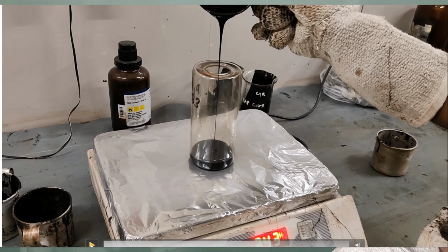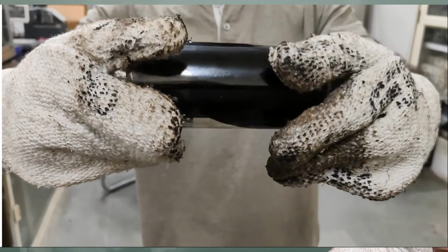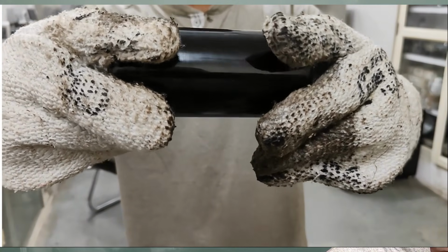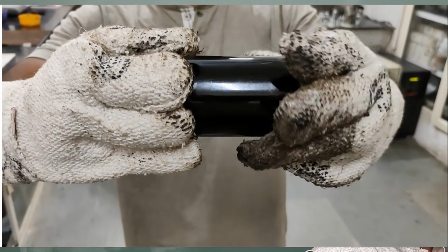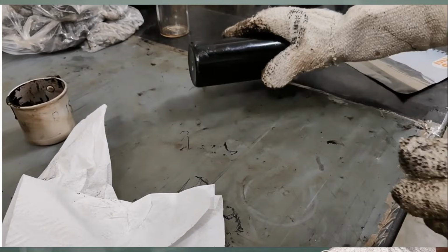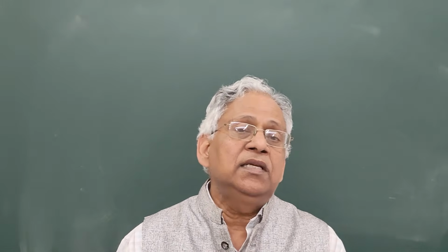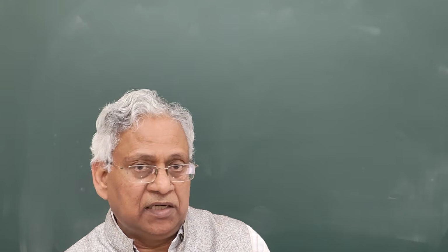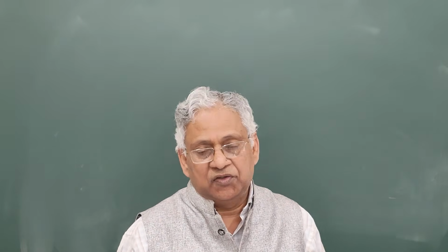Then immediately after pouring the sample, turn the container into a horizontal position. Rotate the container slowly for at least one full rotation to pre-coat its surface. But make sure that the sample does not flow out of the container during this step. Place the container in the horizontal position in the cooling rack at room temperature. Now keep these containers in the cooling rack for 60 to 180 minutes, minimum 60 and maximum 180 minutes, for cooling to room temperature.